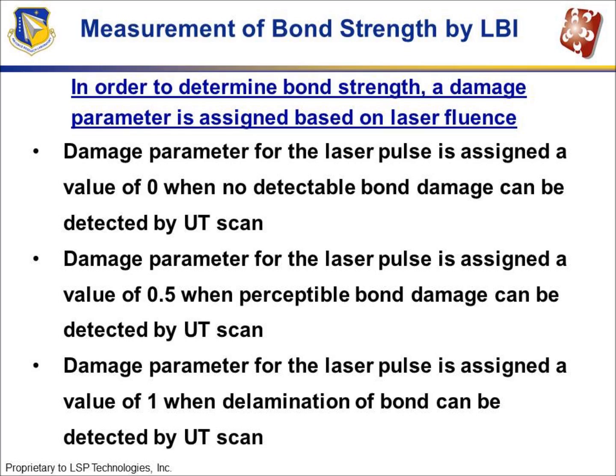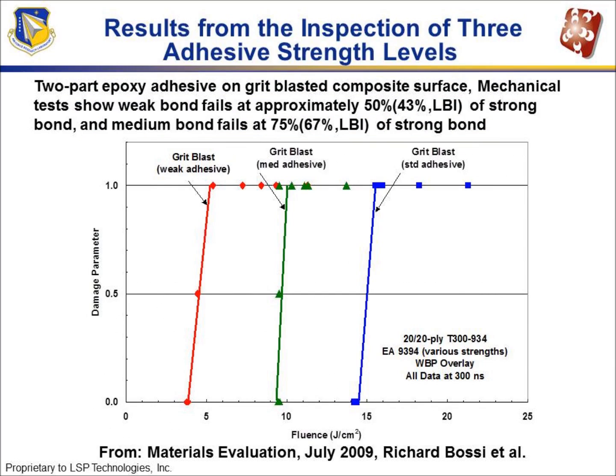Under 5, we see a little bit of damage, so we assign it a value of 1/2. And then above 6, we see a lot of damage and are damaging it consistently. It shows that around 5 joules per centimeter squared, we see damage in the bond line on this sample. We continue on with the next sample, and this has a stronger bond, so it breaks at a higher fluence level. As you see, it's breaking above 10, and the standard bond line breaks above 15.